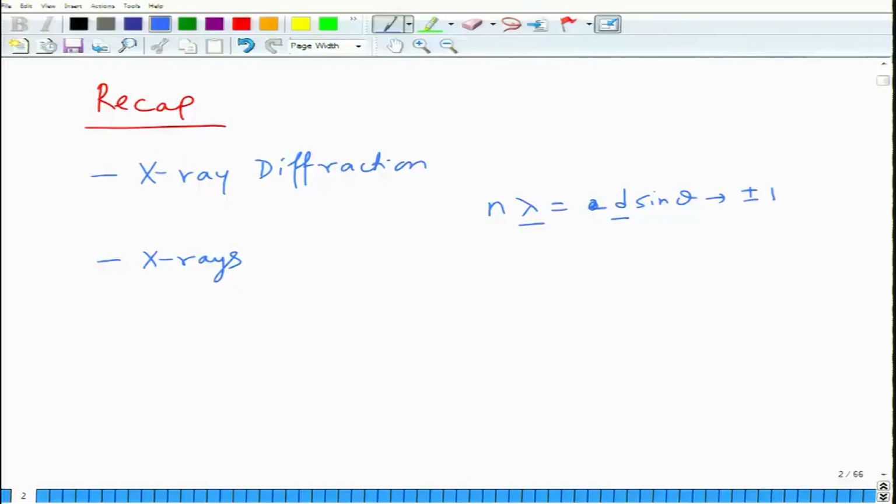That is how these transitions occur. When an electron from a higher to a lower energy level undergoes a transition, it emits an X-ray photon, whose energy corresponds to the energy difference between the two energy levels. So for K alpha, it is going to be the energy difference EL minus EK.